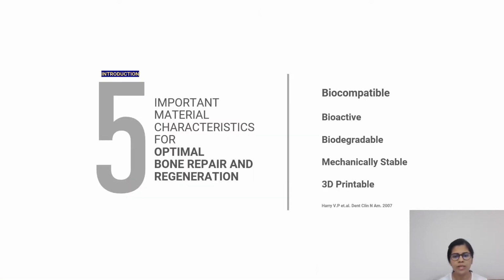So, what should one consider when trying to develop a biomaterial for bone regeneration? These five important material characteristics for optimal bone repair and regeneration should be taken into consideration. The material should be biocompatible, bioactive, biodegradable, mechanically stable, and it should be 3D printable. As we know, the strength has to balance with that of the native bone, because if the strength balances, then that leads to better bone repair and regenerative procedures.